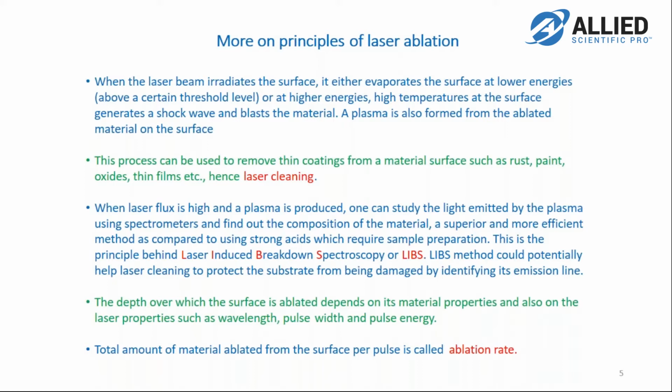We have actually tried this technique with our laser cleaners to look at the spectrum of the substrate and basically stop the laser or move the laser when it sees that spectral line. And it has been pretty successful, and we are trying to integrate that into our system.